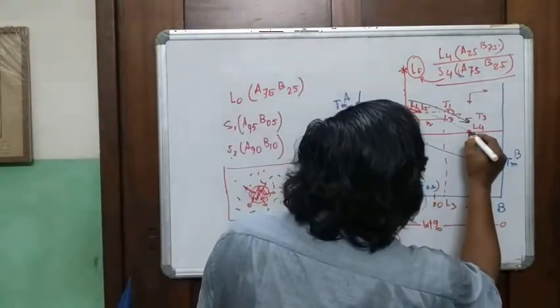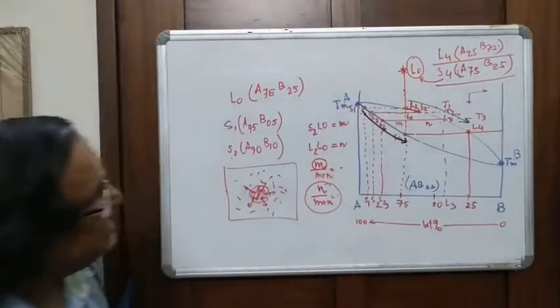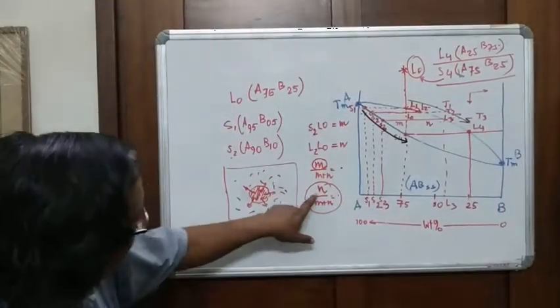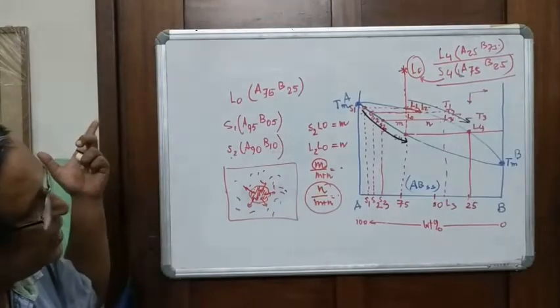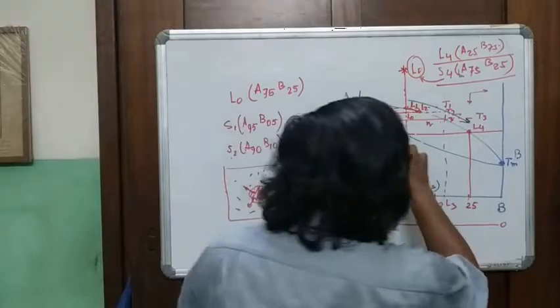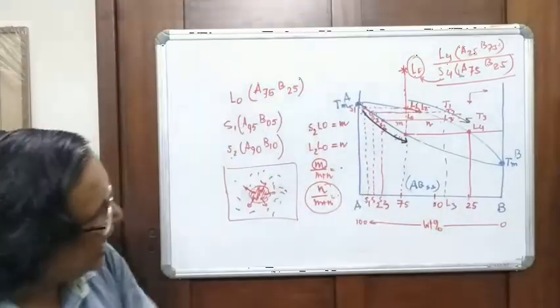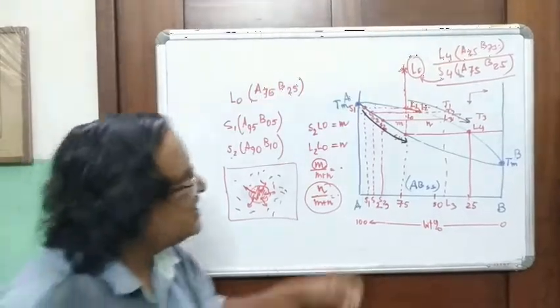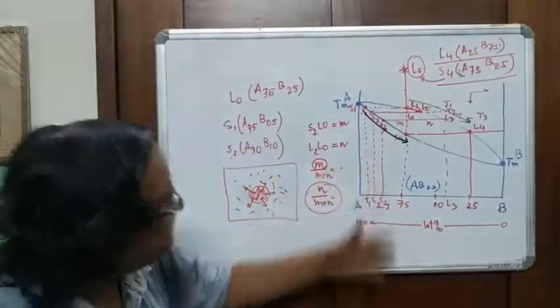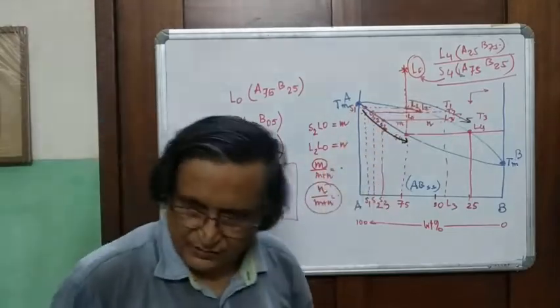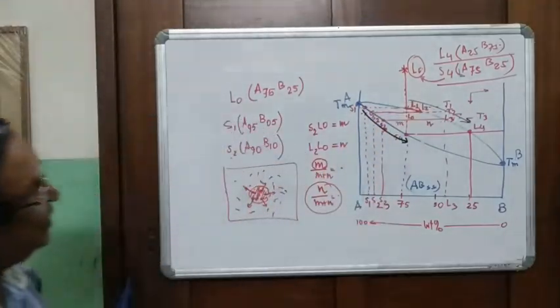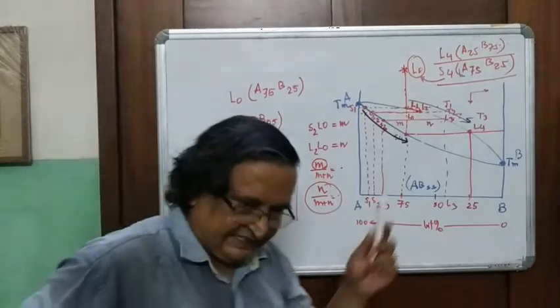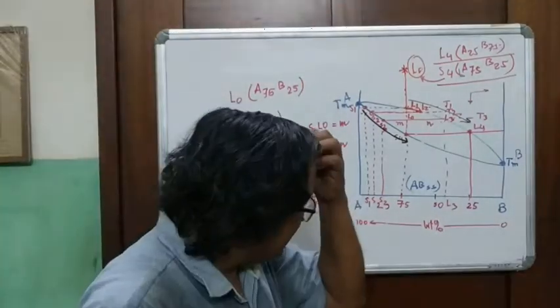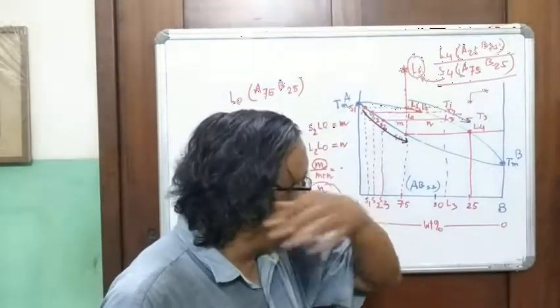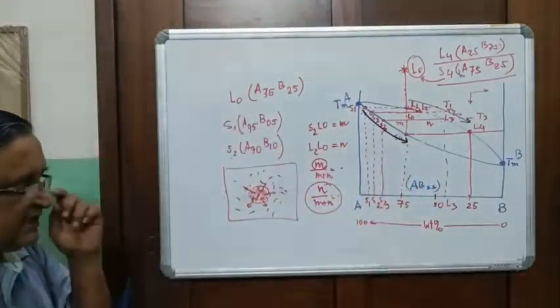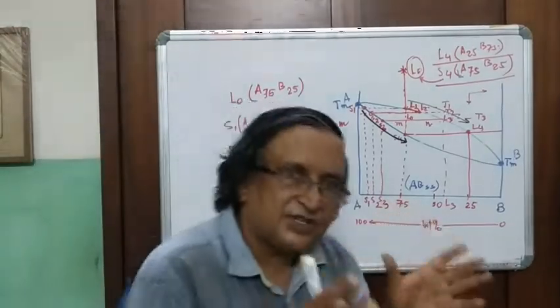You see here, at this point, your M is almost equal to 0. There is no M because the fraction of liquid is almost gone, because the whole is now totally N. So your last fraction of the liquid is gone. This is how crystallization happens in a solid solution phase. There are many facets to this, but we will discuss this in a different context. We will not discuss this now. First, let us concentrate on equilibrium crystallization.